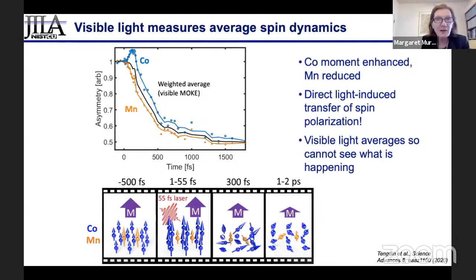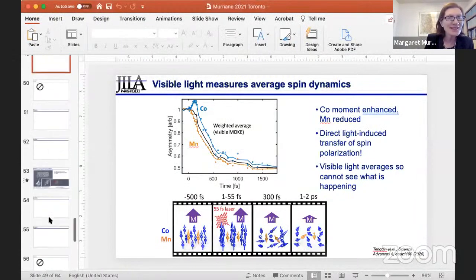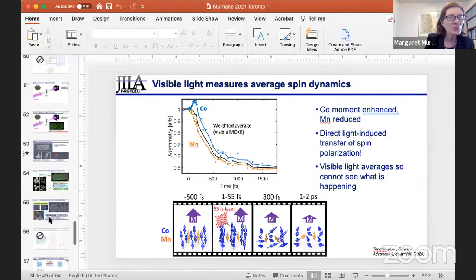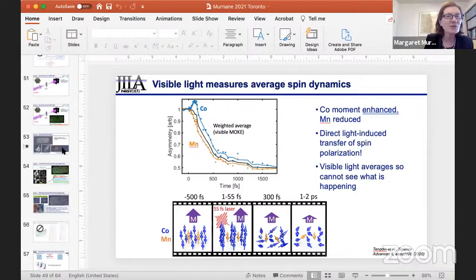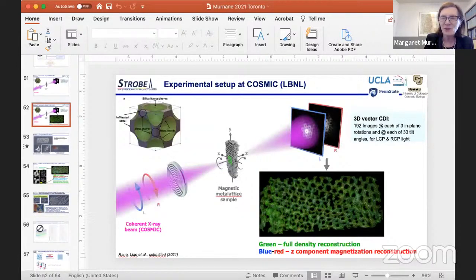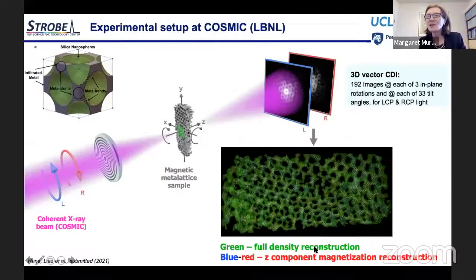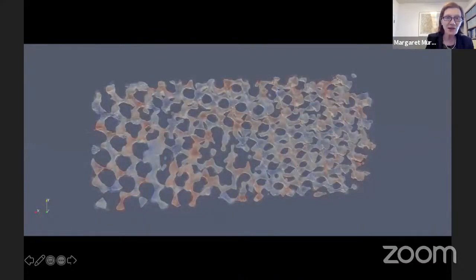So with that, I am going to move on to wrap up. Maybe I'll show you one highlight in the last minute of work done at COSMIC, where we worked with Jianwei Miao's group, Penn State, David Shapiro and others, to now, instead of looking at spin dynamics, look at spin texture. So we took a synchrotron beam and focused it onto a nanostructured nickel material. And then through doing a whole lot of data collection, tomography and vector tomography, where we used magnetic circular dichroism to get contrast. And I'll just finish by using this movie showing this.